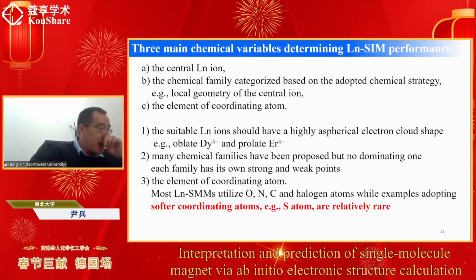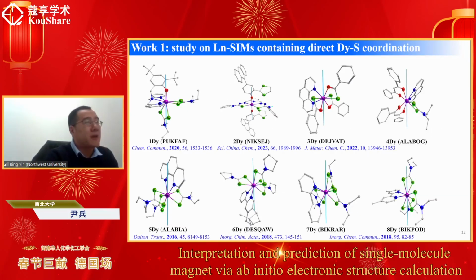And in the case of the element of the coordinating atom, most lanthanide single-molecule magnets utilize the so-called hard donor coordinating atoms, for example, oxygen, nitrogen, carbon, or halogen. While examples adopting soft coordinating atoms, for example, sulfur atoms, are relatively rare. But there have been some reports of lanthanide single-molecule magnets having direct lanthanide-sulfur coordination. There are some examples shown here. And some work with direct lanthanide-sulfur coordination gives good single-molecule magnet performance, so there is some optimistic prospect for such kinds of systems.